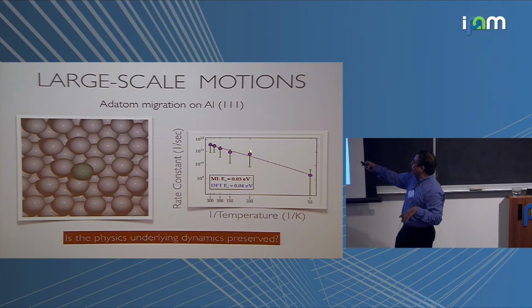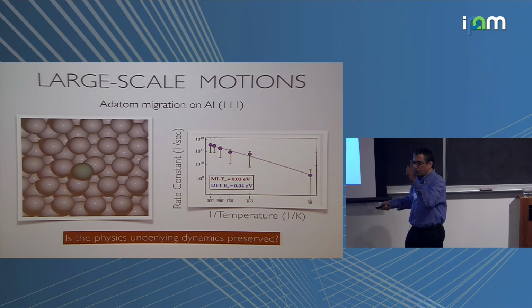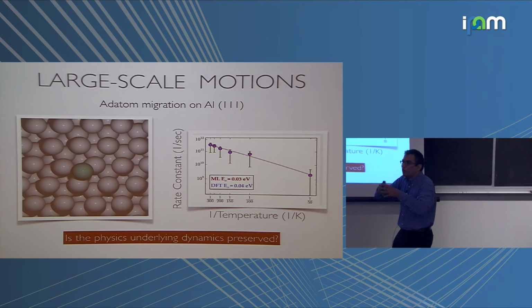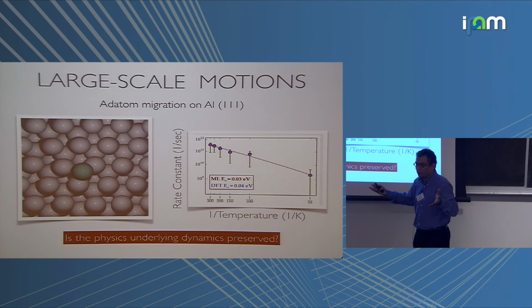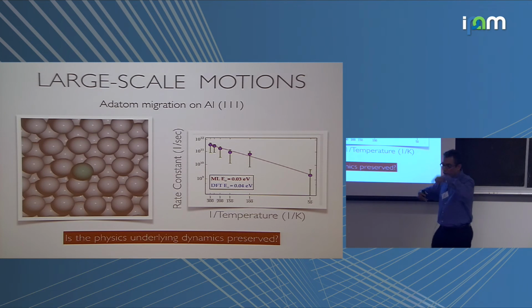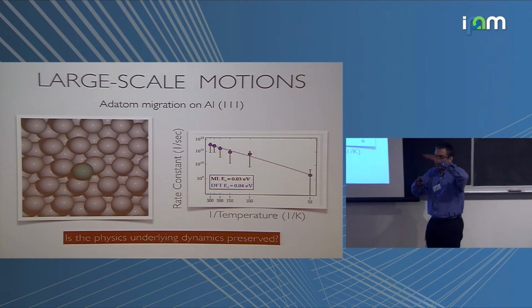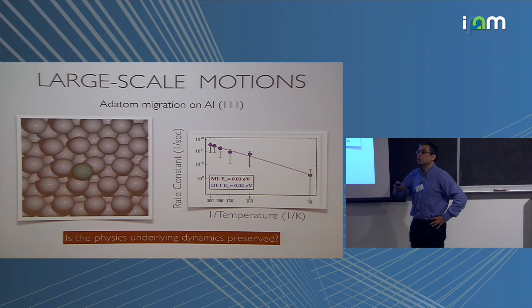The error bar is because we cannot come up with one average rate. For the average hop time, we have a distribution of hop times for each temperature, right? That's why there is an error bar. We just show the range of the uncertainty in the hop times. Not the standard deviation, what is the range?